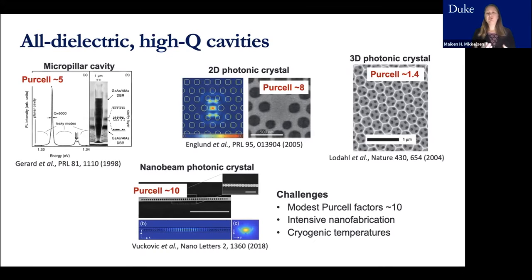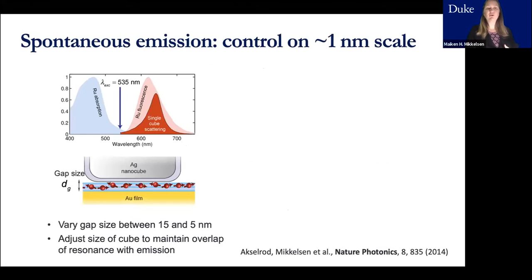So we're interested to see if we can use plasmonics to achieve large enhancement in the spontaneous emission rate. While there were a lot of reports in the literature already, some reporting high enhancements, some quite low enhancement or even quenching, what was really missing, we thought, was a systematic study to probe the mechanisms behind it and how we can achieve large Purcell enhancement in a reproducible and very predictable manner. What we found was that control on the single nanometer scale of the critical dimensions really matters.